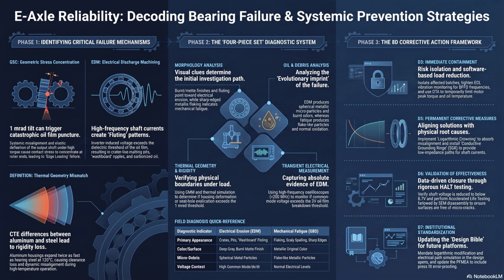Mechanical fatigue looks completely different. Entirely different. Fatigue shows irregular, flake-like spalling. The metal physically tears away. The flakes often look like tiny arrows pointing in the rolling direction. And Appendix B in the document even notes a color difference. Fatigue damage keeps its shiny metallic color, while electrical erosion looks burnt, black, or flat gray. So that's the visual fingerprint.